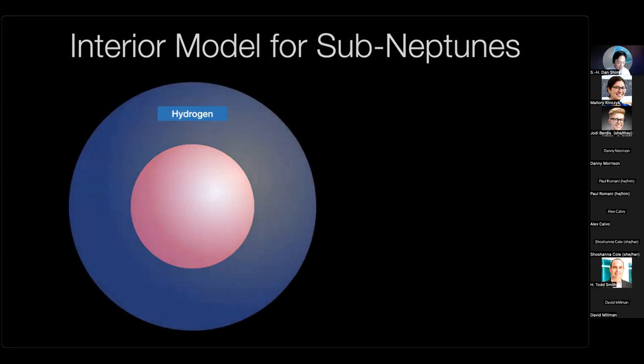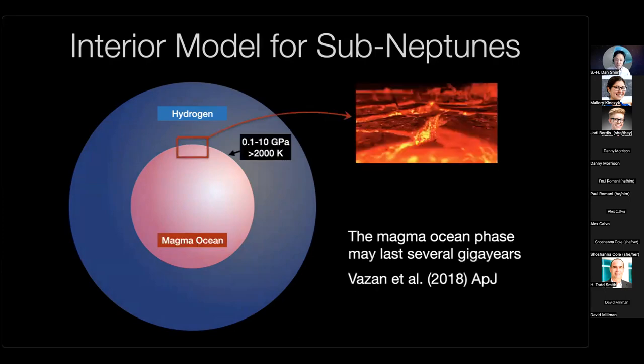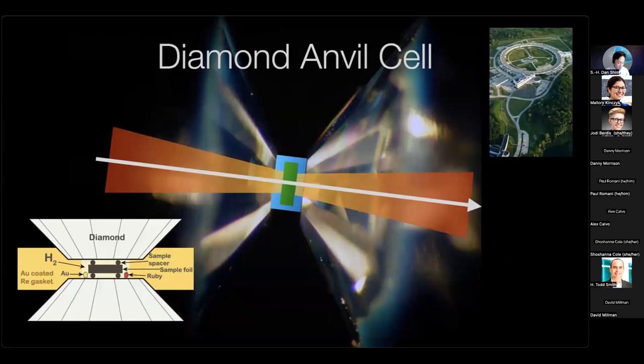If the mass-radius relation of the sub-Neptune is entirely explained by pure hydrogen or a hydrogen-rich atmosphere, then you can calculate the pressure conditions from the mass-radius relations, which range between 0.1 and 10 gigapascals. And this thick hydrogen atmosphere has enough of an insulating effect that theoretical studies have shown that the rocky core will maintain a molten state for billions of years. That translates to a temperature of about 2000 Kelvin or higher at the interface between the magma ocean and the hydrogen atmosphere. With that, we can design a high-pressure experiment.